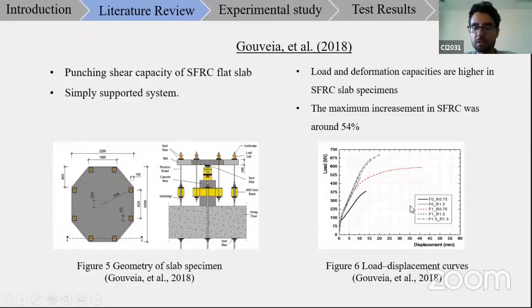They tested 5 specimens. The number after the letter F represents the steel fiber ratio, and the number after the letter R represents the flexural reinforcement. As you see here, the load and deflection capacity are higher in steel fiber reinforced concrete specimens compared to the one without steel fiber reinforcement. And this shows that fiber gives an important contribution to improving the behavior of flat slabs. As the fiber content increases, the load and deformation capacity increase. The maximum increase in steel fiber reinforced concrete was around 54%.